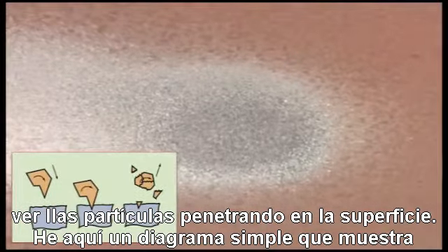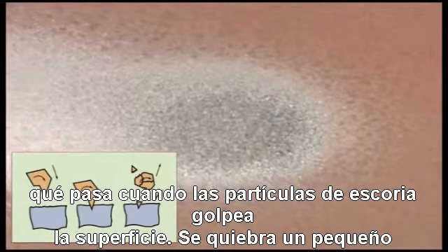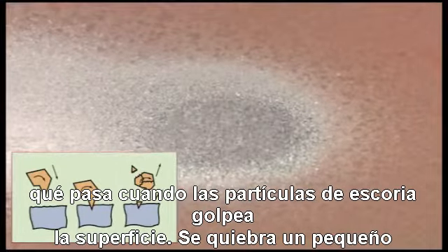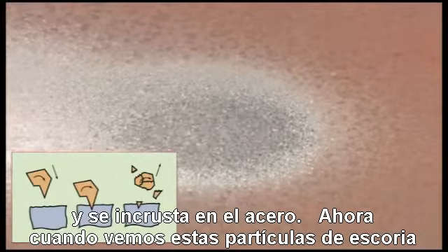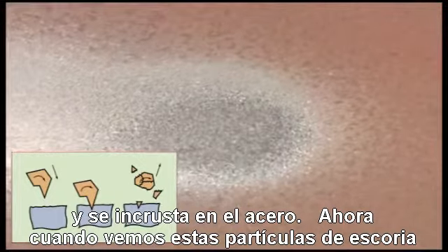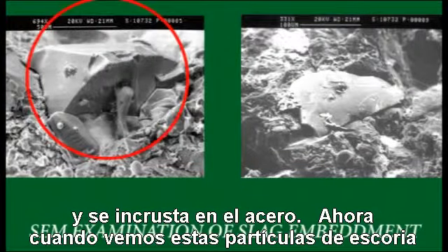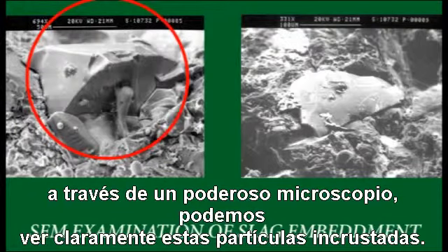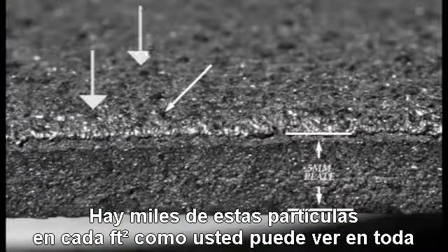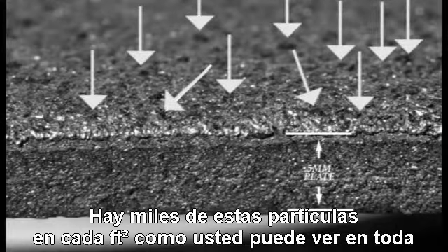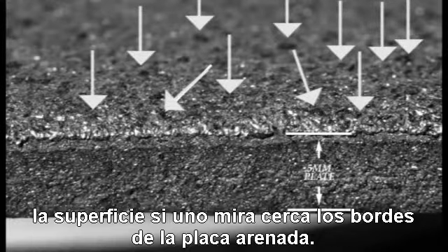Here is a simple diagram which shows what happens when the slag particles hit the surface. A small piece of slag breaks off and embeds itself into the steel. Now, when we look at these slag particles through a powerful microscope, we can clearly see these embedded slag particles. There are thousands of these particles in every square foot, which you can see are scattered all over as we look closely at this 1/4-inch plate.